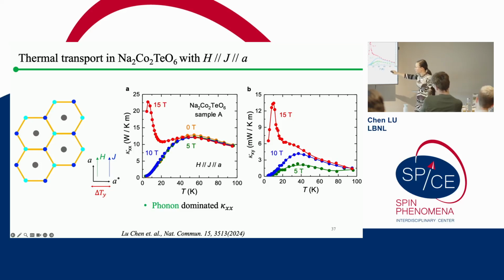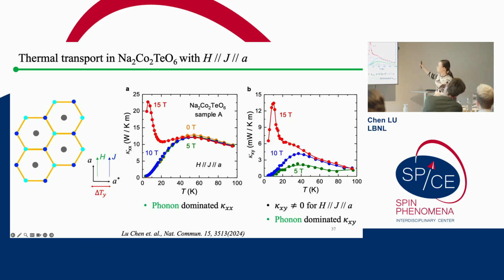Figure B here is the thermal Hall conductivity versus temperature taken at 3 different fields. First of all, we got a non-zero planar thermal Hall effect for this material. And the second thing is, if you compare panel B with panel A, you will see their temperature dependence is very similar, especially when you compare 10 Tesla to 15 Tesla. When thermal conductivity shows a strong enhancement at low temperature and high field, thermal Hall conductivity shows the same thing. This is a strong indication that whatever heat current gave you thermal conductivity should be responsible for the thermal Hall conductivity. This is a major argument: we try to argue that this thermal Hall effect is actually dominated by phonons.